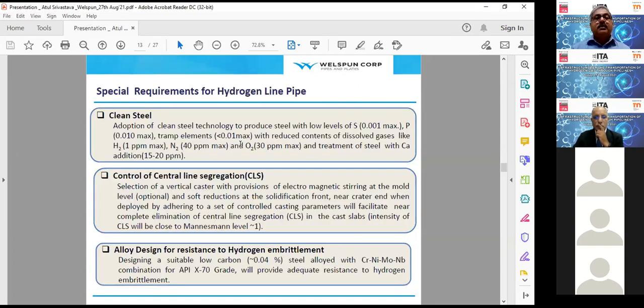It is a sum up, an absolute clean steel. The numbers are given for the sulfur, phosphorus, tramp elements, control of centerline segregation. That is very, very important. And alloy design for resistance to hydrogen embrittlement should be such that the carbon is low, with a combination of chrome, nickel, moly, niobium for a grade something like X70. So next slide, sir.